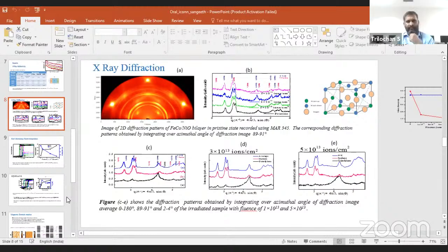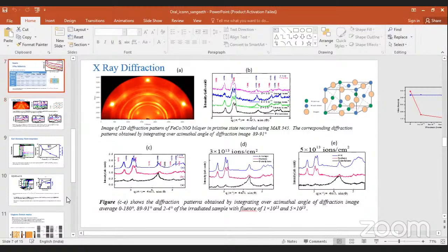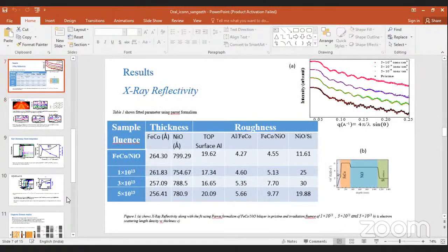What is the thickness of the film? Sir, the nickel oxide is 80 nanometers and the FeCo is 30 nanometers.